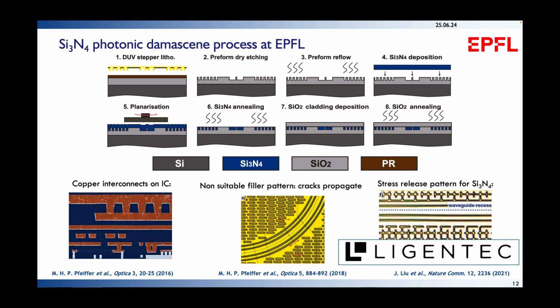You use it actually to make electronic interconnects, where instead of filling the patterns that you etch with the dielectric material as done here, you fill them with copper. And use exactly the same step of the polishing. So this copper damascene process we actually employ in integrated photonics, and we can make that way very tightly confining, low-loss integrated photonic circuits that we commercialized with Ligentec about 8 years ago. And these actually are now manufactured in state-of-the-art 200mm lines in the X-Fab in Paris.